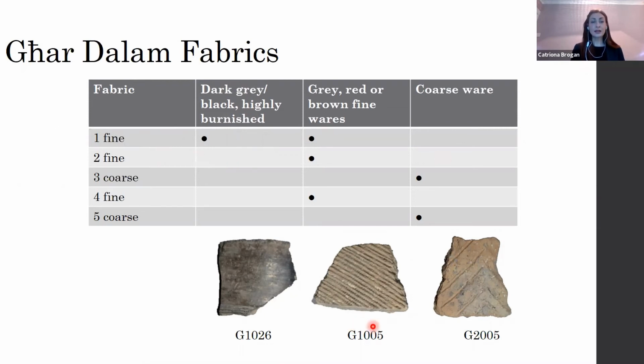Then we looked at the other fabrics that we have, and basically all of the fine wares were used to construct this type of Għar Dalam pottery, which is quite a common style. Basically, it tends to be grey or a reddy brown in colour, and it's often highly decorated as well. So this accounts for the other fine ware fabrics. And then lastly, we have these coarse vessels, which tend to be very thick, and often the decoration on them is quite coarsely executed. With these, rather unsurprisingly, perhaps, they are associated with the two coarseware fabrics that we identified.